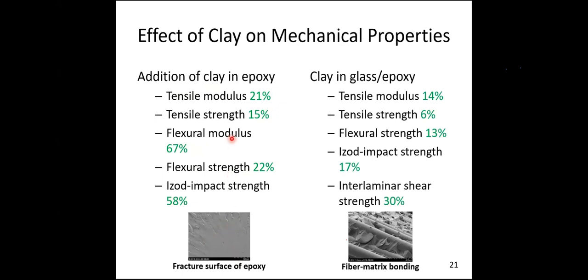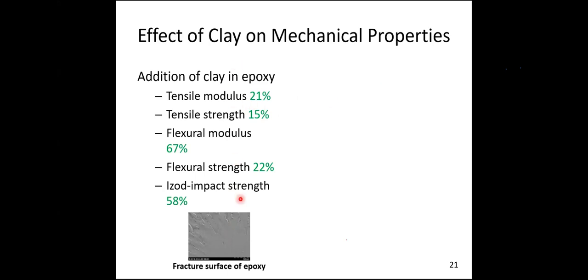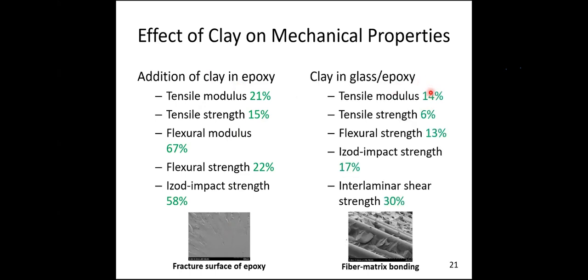So now we have also carried out similar testing for composites. If you see, this left hand side shows the effect of clay in polymer. We also wanted to understand the effect of clay in a typical composite. So what is a composite? A composite should have a reinforcement called fiber, and it should have a matrix called polymer. So we used a glass fiber reinforced polymer for this study. We also tried different clay compositions. Again, if you see on the right hand side, we have got some minimal improvement of the mechanical properties with the addition of clay in the glass epoxy composite. So you may ask a question.